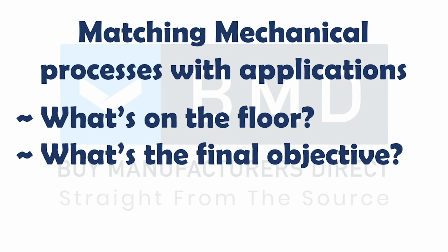profile. If, as an example, a floor has a thick epoxy on the concrete and grinding alone is taking too long, then it's definitely possible to use the PCD that I spoke of or the scarifier to remove the bulk, because what we're really talking about is a certain thickness of material on top of the concrete that grinding alone is not going to be productive enough to remove.